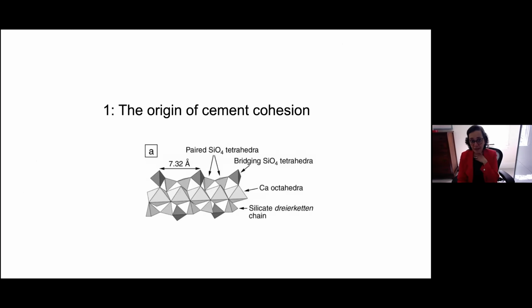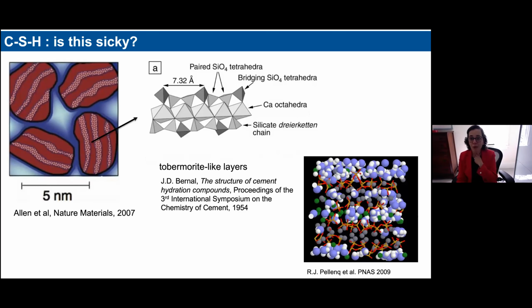So why is this material sticky to start with? Well, you have these nanoparticles that precipitate. And in fact, even at the very small scale, cement is a particularly complicated material. I said that the nanoscale structure is really similar to a rare mineral called tobermorite, although with tobermorite you cannot actually make cement. And this has been studied. There is now a large literature on atomistic simulation of this material.